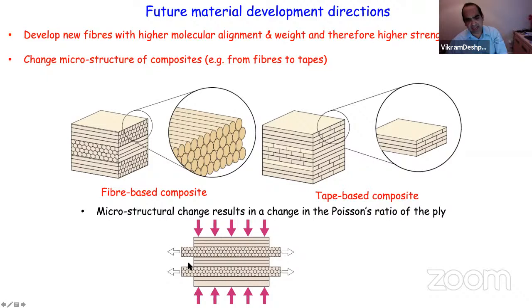Now, the reason we were getting failure by that indirect tension mechanism is this Poisson effect, where effectively these layers of the composite were trying to expand by a Poisson effect and were putting these into tension. If you reduce this Poisson effect, then you're going to reduce the amount of tension generated in these layers here like this. And that's what the tape-based composites are hopefully going to do for us.